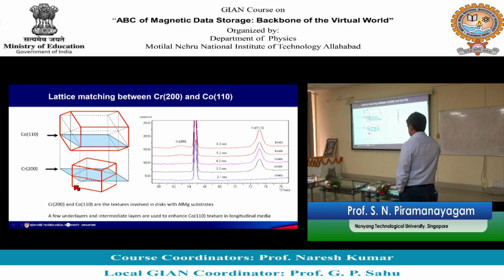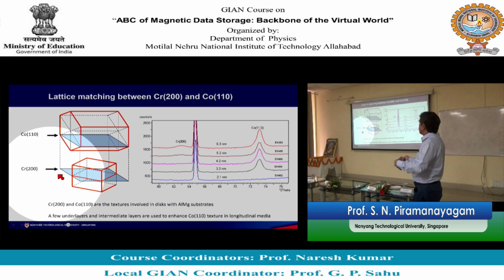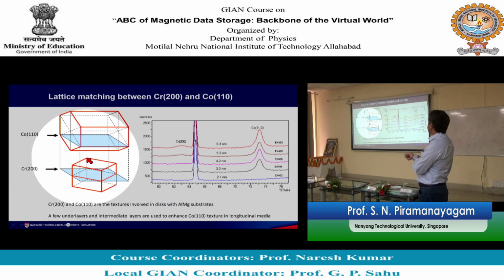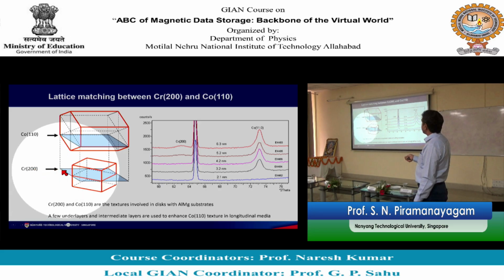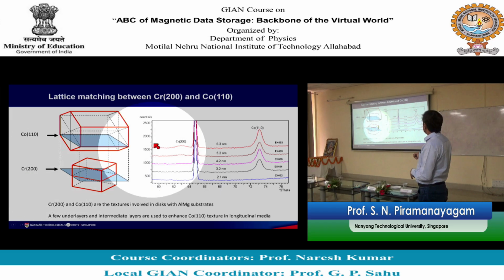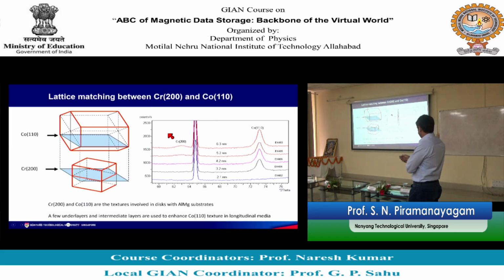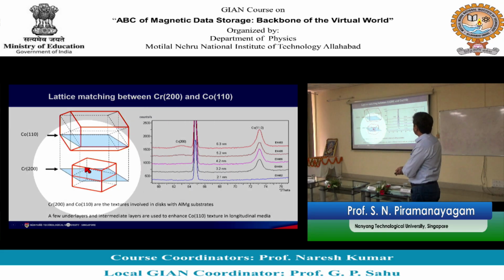If you take substrates like aluminum-magnesium, and you deposit chromium at a temperature of around 250 degrees Celsius, then you can grow most of the chromium grains to have the 200 plane parallel to the substrate. If you do XRD, you will see peaks like this. You see chrome 200 is parallel to the substrate, and the chrome 200 has a lattice matching to cobalt 110.